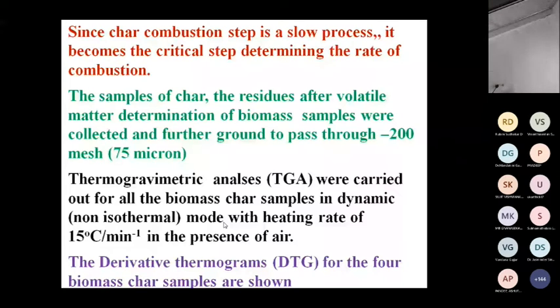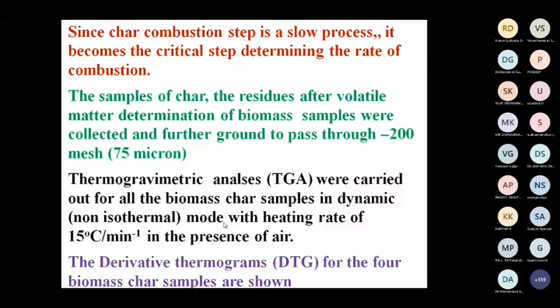So if you want to study the reactivity of the fuel, you can eliminate VM, because it is sufficient to study the char combustion, as char combustion is going to be the determining step. The char residues after volatile matter removal from the biomass samples are collected. Then we are studying the char kinetics using TGA. Earlier we saw the raw fuel. Now we have prepared the char after removal of volatile matter. Then char studies were made using TGA. Thermogravimetric analyses were carried out for biomass char samples in a dynamic non-isothermal mode with a heating rate of 15 degrees per minute in the presence of air.